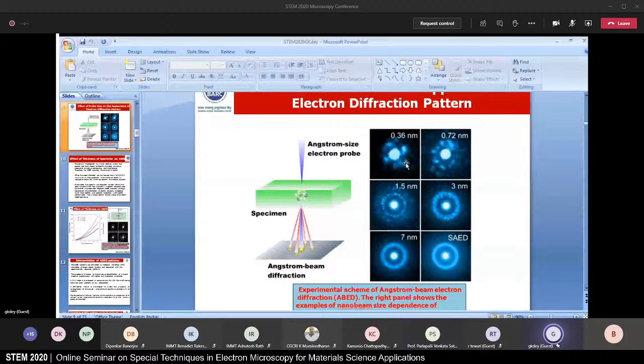That is because you are examining the symmetry of one cluster of atoms. So how do you examine one cluster of atoms or two clusters of atoms? That is very important. You cannot have 5 clusters together, because then you will have all the diffraction patterns superimposed on each other, and that is the result in SAD, because you are examining many clusters at the same time. So the thickness of the sample becomes important, and this slide shows the importance of the thickness.